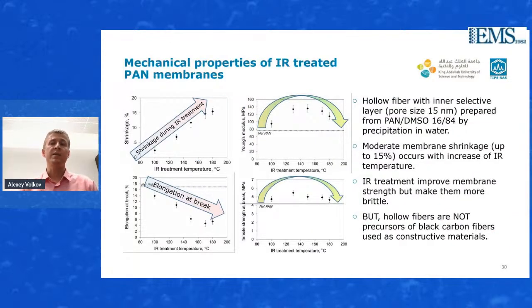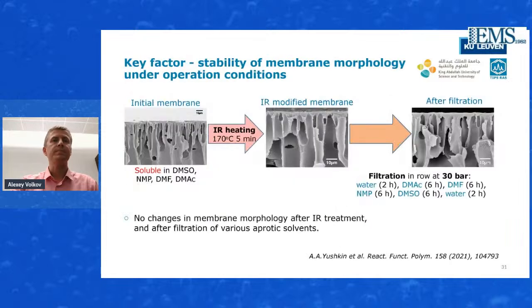And in terms of the mechanical properties, we don't actually have quite a big loss of them, which might still be attractive for the fabrication of the membranes, which can still be used as they are. And the most important thing is that we did a filtration of the membrane in a range of different solvents, but analysis of the cross section of the initial membrane, and after modification and after filtration, demonstrated that infrared treatment does not change the morphology of the membrane, which is important because the post-treatment might also change the properties of the membranes, and which also requires optimization of the casting conditions before that.